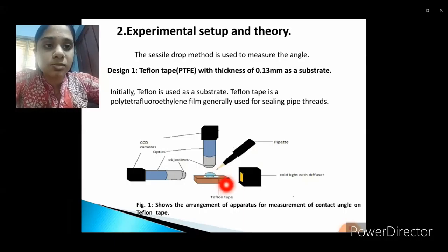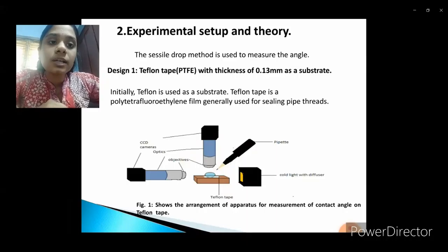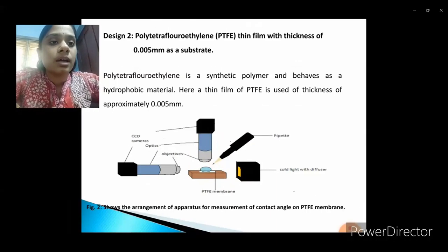Initially, when the drop is placed on the substrate, the images are taken and the contact angle is determined, and then the voltage is applied. The same procedure is repeated for the second substrate with a thickness of 0.005 millimeter. Here is the schematic representation of that. This is just a schematic representation. The actual experimental setup that we have used is like this. This is the contact angle meter, this is the power supply, and this is the temperature controlling unit. On this screen, we have captured the images.